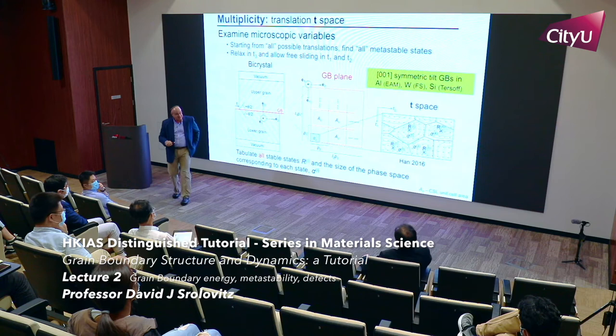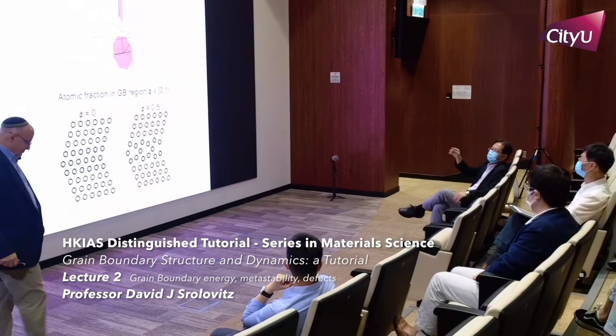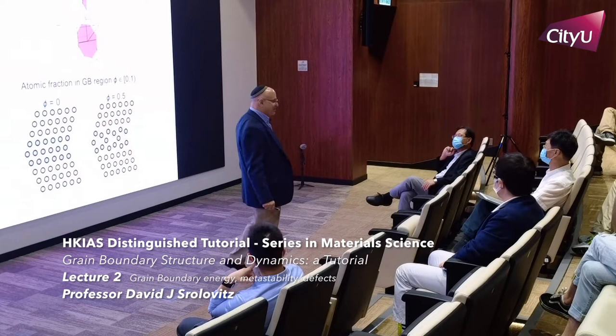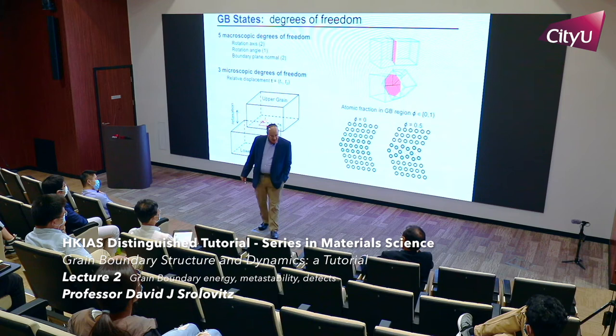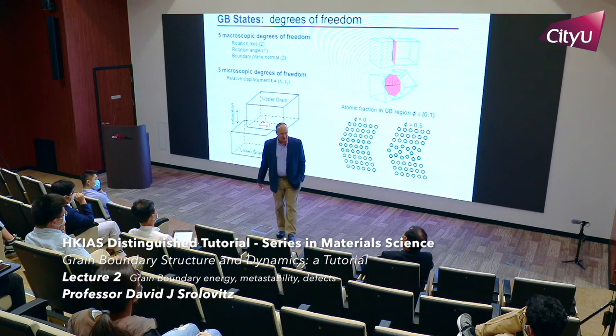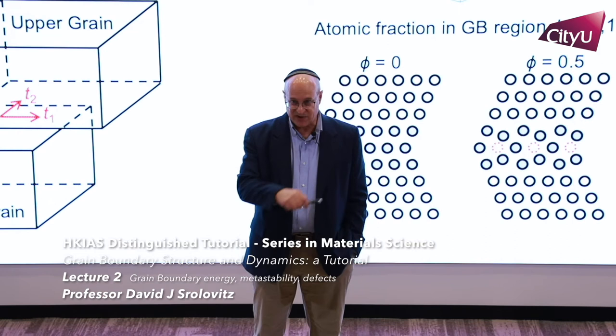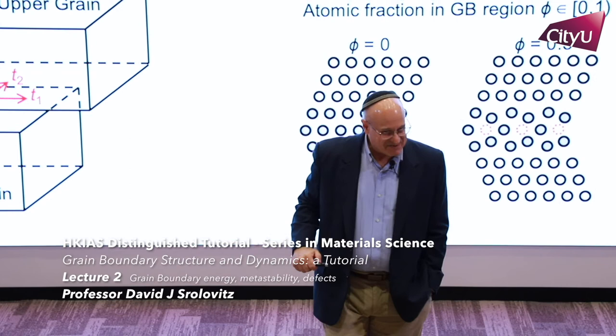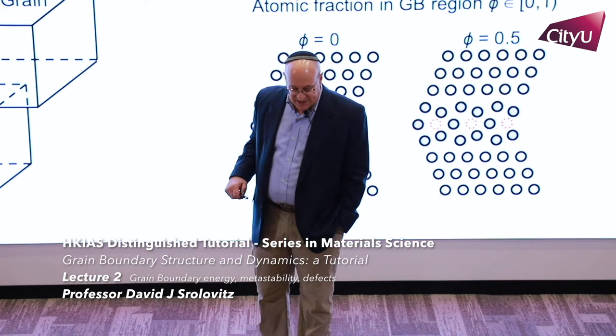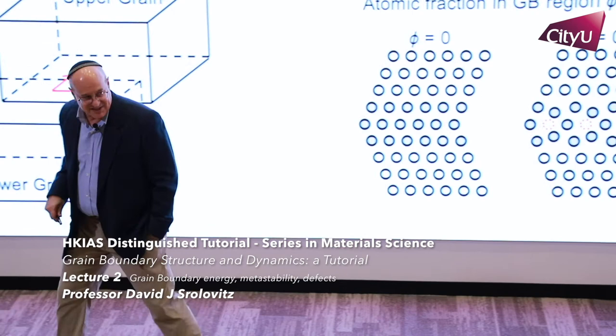Question about diffuse boundaries: If I'm talking about the five macroscopic degrees of freedom, it says absolutely nothing about the structure — diffuse or not diffuse doesn't matter. For the microscopic degrees of freedom, it tells you how atoms are arranged along the grain boundary. Some grain boundaries are wider than others. 'Diffuse' is a diffuse term — it just means the boundary is not atomically sharp. All the crystallography still applies; it's just harder to visualize.